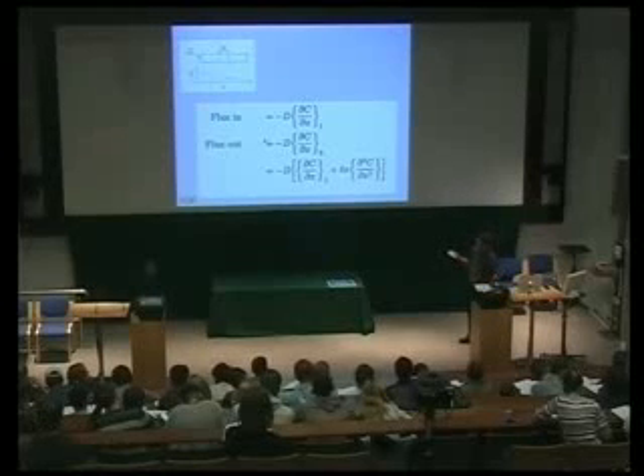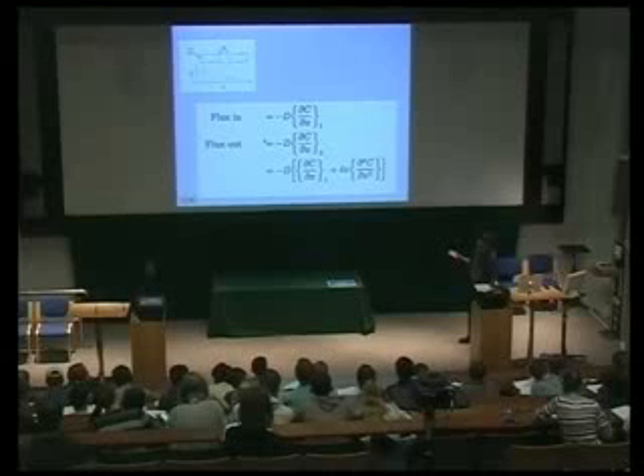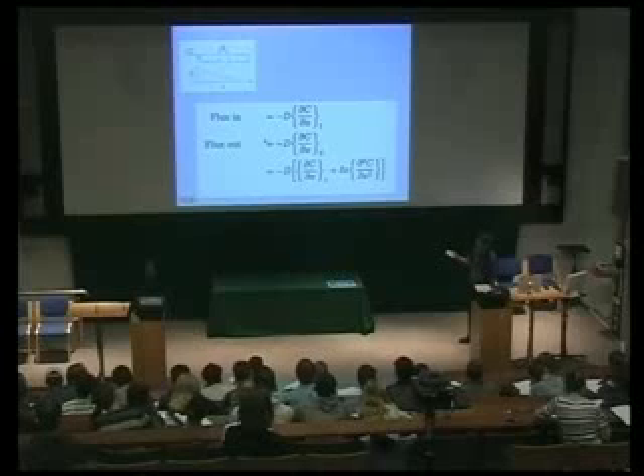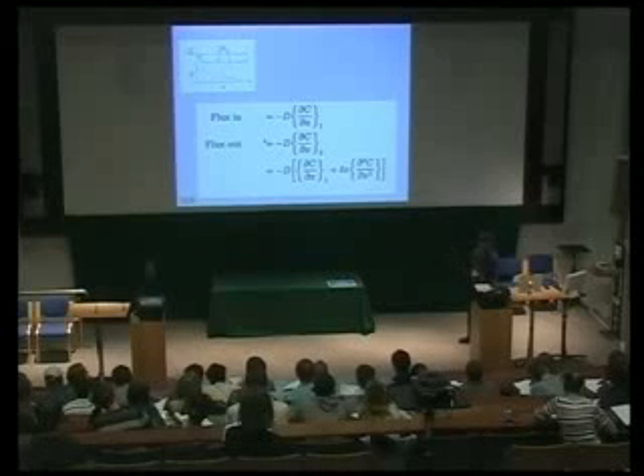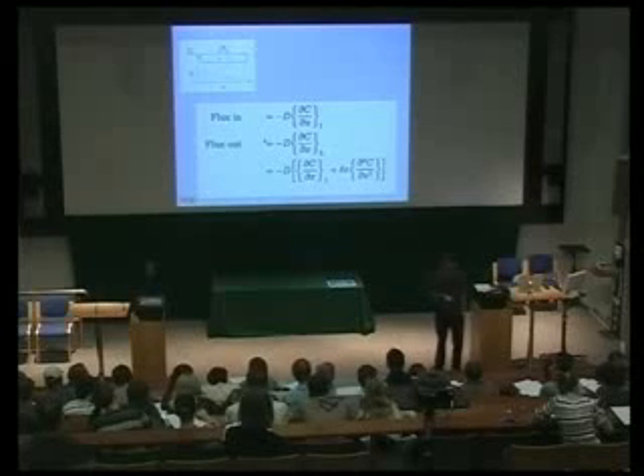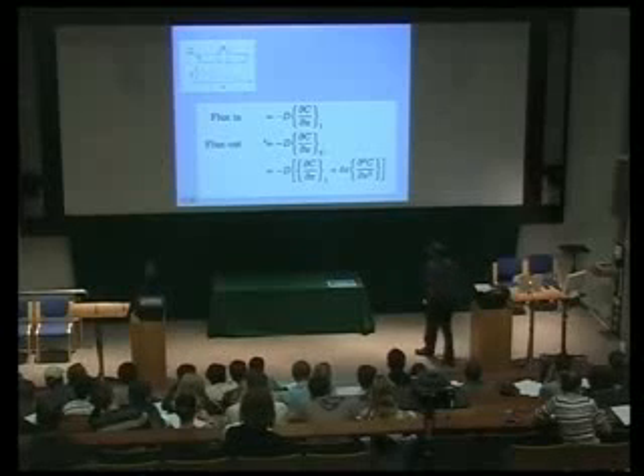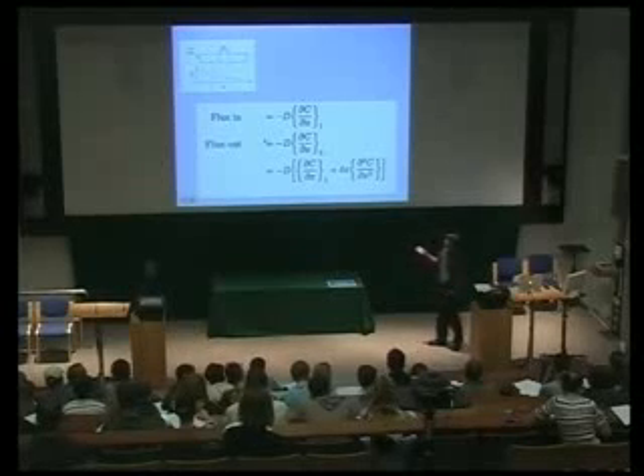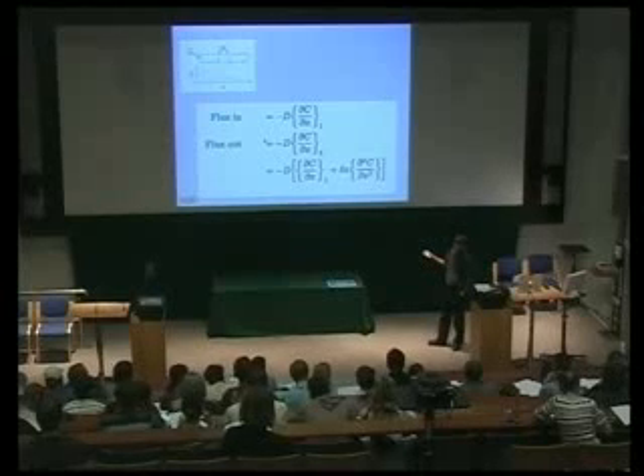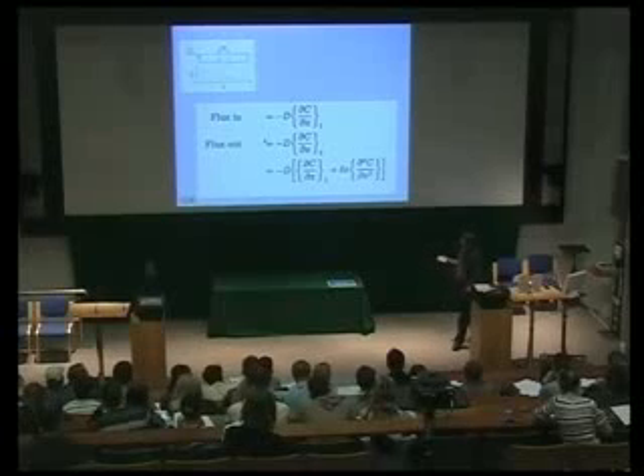Okay, so the flux going into plane 1 is simply the diffusion coefficient times the gradient, and this time I've got a subscript 1 here to indicate that this is the gradient at position 1. Previously we didn't need to use that because the gradient was constant. For plane 2, the flux will depend on the gradient at location 2.